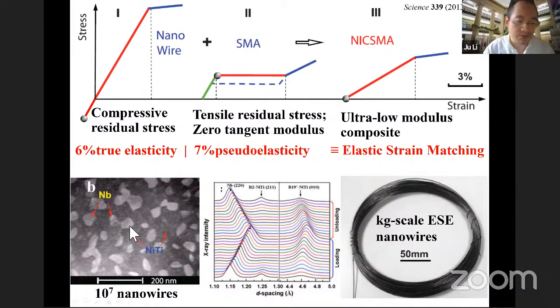Remember, the whole reason we have high elasticity in this nanowire is because we suppress dislocation nucleation. But if you have dislocation which is piled up on this interface, boom, you would reduce that strength limit. But if you have this B2 to B19 prime phase transformation, at the atomic level, it's only 7%. So that's a much blunter inelastic deformation, and that preserves the good elasticity of the niobium nanowires. So we call this the elastic strain matching design idea.